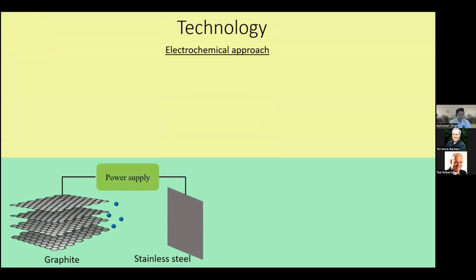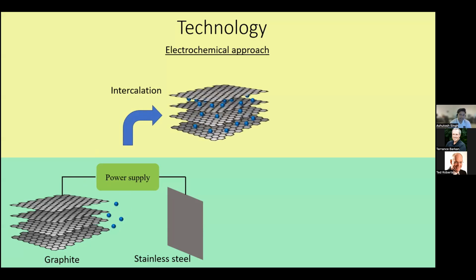Going into the technology, as I mentioned, it's an electrochemical process. What we do is have two electrodes, one of them being graphite and the other a counter electrode, which could be stainless steel or any other metal, usually exposed to a salt solution. The ions from the salt inside the water are solvated with water molecules. You can imagine these blue dots as ions in the salt. When you apply current between these two electrodes using your power supply, it creates an electric field which pulls the ions between the layers of the graphite. This process is called intercalation. As the ions intercalate, you can see the graphite expanding through the reaction.